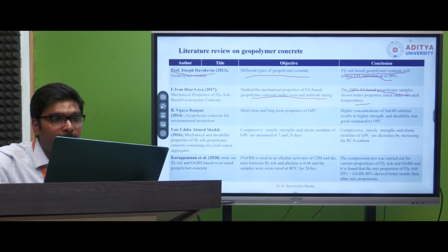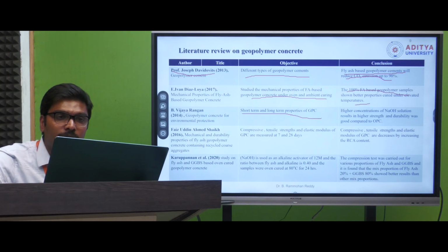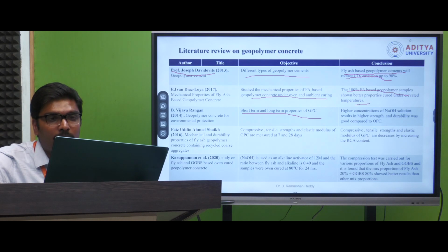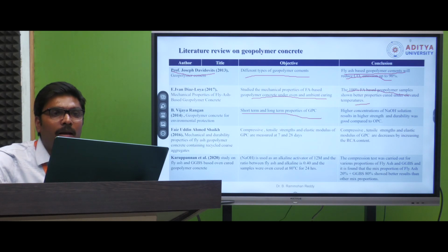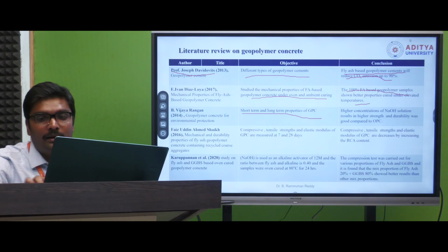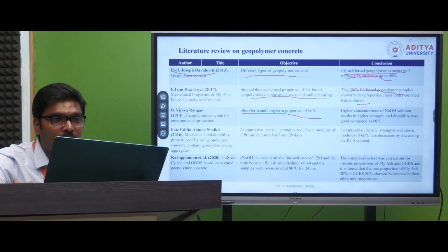And in another study, long term and short term properties of geopolymer concrete were carried out, and he concluded that higher concentrations of sodium hydroxide solution resulted in high strength and durability as compared to OPC. So the concentration of NaOH also plays a major role in the attainment of enhanced strength and good durability properties of geopolymer concrete. Like this, many researchers have shown geopolymer concrete is an effective alternative to conventional concrete.